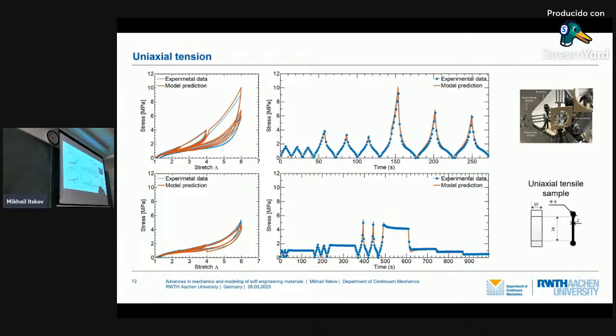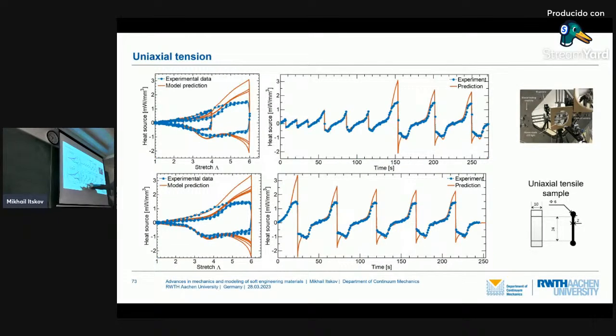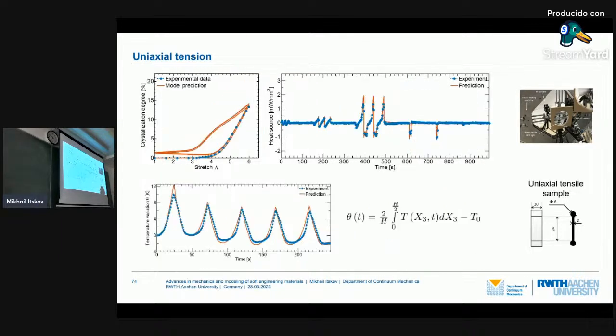This agreement is obtained automatically, for example, for this cyclic test with stepwise increasing amplitude, and also here with preconditioning. The only problem you see is in the description of the heat source. We have rather good agreement at middle values of stretches, but at very high stretches our model overestimates the heat source, but we believe that is due to the fact that we don't consider the internal energy of the polymer segment. The temperature evolution here, for example, is rather well described, and here also the crystallization degree, where we have good agreement with the results.